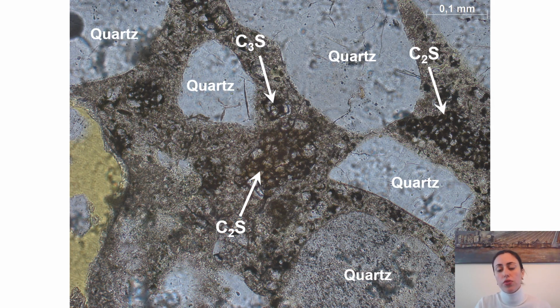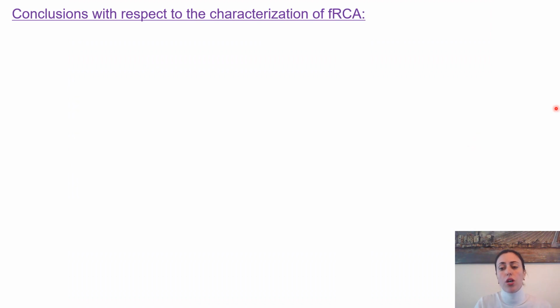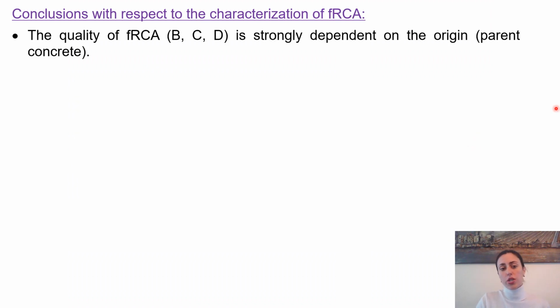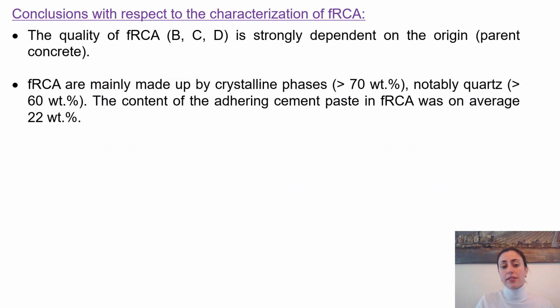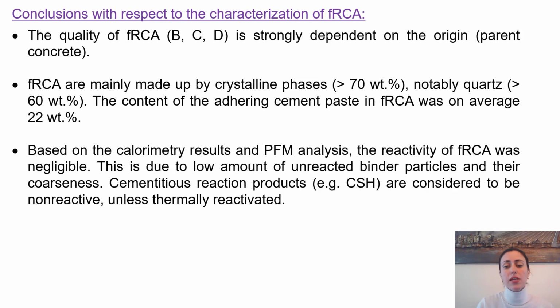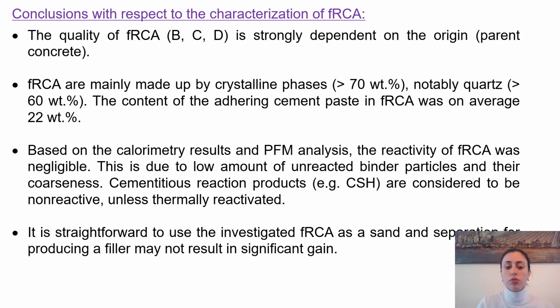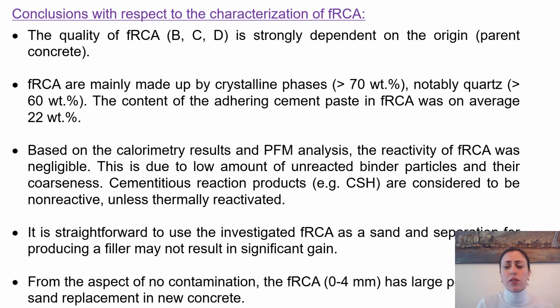I would now like to conclude on the study. The quality of the recycled sand is strongly dependent on the origin, and the recycled sands are mainly made of crystalline phases. The details you can find in the paper, and notably there is quartz, and on average there is 22% of cement paste. As I said, the reactivity was negligible, and this means that this recycled sand can be straightforwardly used as sand replacement in new concrete, and from the aspect of contamination, it has a large potential for use in new concrete mix designs.